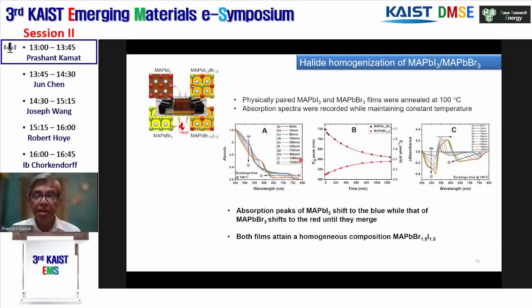And as you heat up and with time, this iodide peak shifts to higher energy and the bromide peak shifts to lower energy, giving you this mixed halide peak. And we can track the decrease or this shift and you can get kinetics information. And this again shows you how the Eg peak shifts in this direction. And this is a difference absorption spectrum that I showed based on this. So we can get kinetic information.